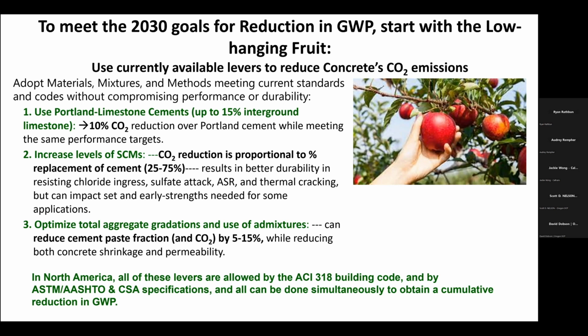Increased use of SCMs, and the CO2 reductions are proportional to the replacement level. And they also result in better durability in most cases to chloride ingress, sulfates, ASR, and improve resistance to thermal cracking. Now, there may be some early strength issues, as I mentioned, but you can design around that.